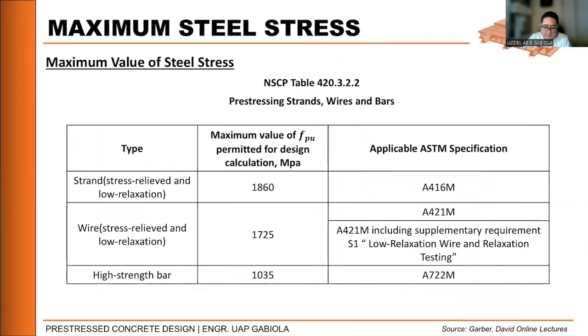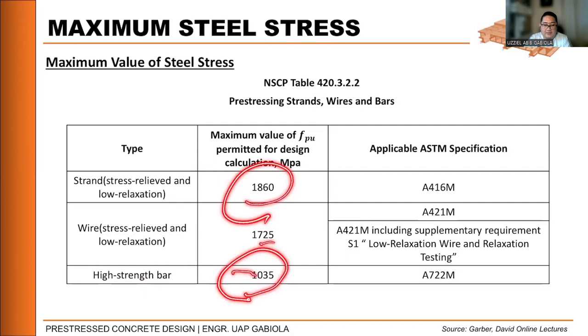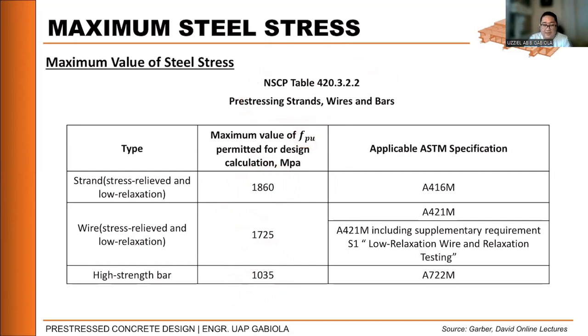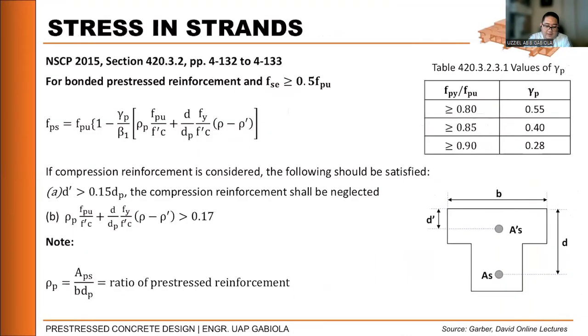For maximum steel stress, according to NSCP Table 420.3.2.2, the prestressing strand has a maximum permitted design value FPU. Depending on the type of tendon — strand, wire, or high-strength bar — the maximum FPU for strand is 1860 MPa, for wire is 1725 MPa, and for high-strength bar is 1035 MPa. If FPU is not given in the problem, use these table values.